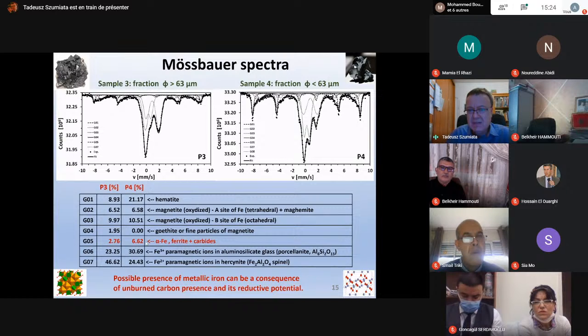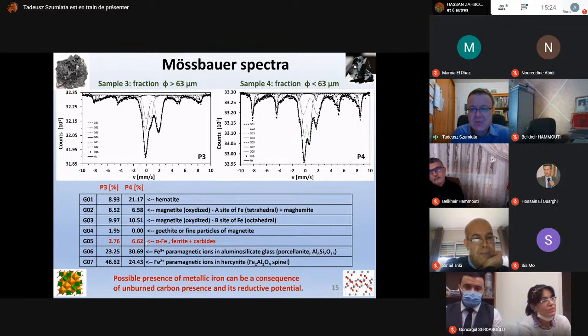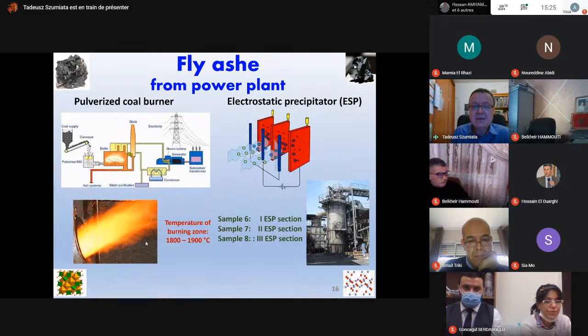Possibly in fly ash we can have unburned coal, and coal has, of course, a reductive potential. So we can expect a kind of metallurgical process, a reduction of some part of iron oxides, and that's why we can see, of course, very small particles of metallic iron here.